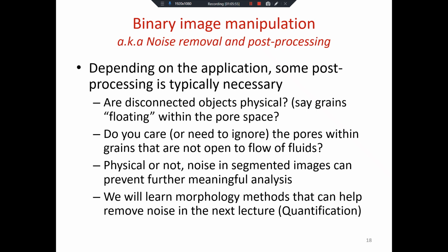The largest feature in your image determines what the overall permeability will look like to an extent. So removing small features will not affect permeability all that much, so you can safely remove them. However, if we're looking into surface reactions, small features tend to be near surfaces. That's where you have a lot of errors, a lot of noise. That can disproportionately affect your simulation or the interpretation of the results. So you have to be a little bit careful.